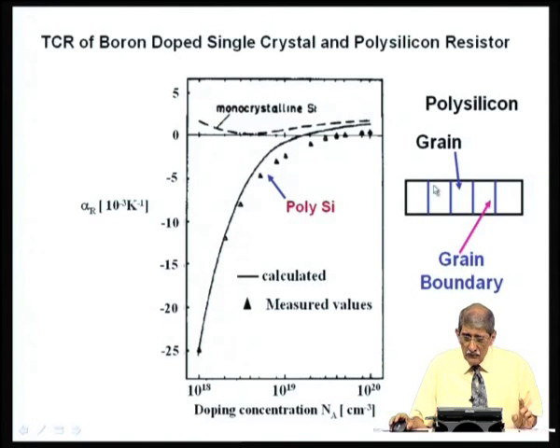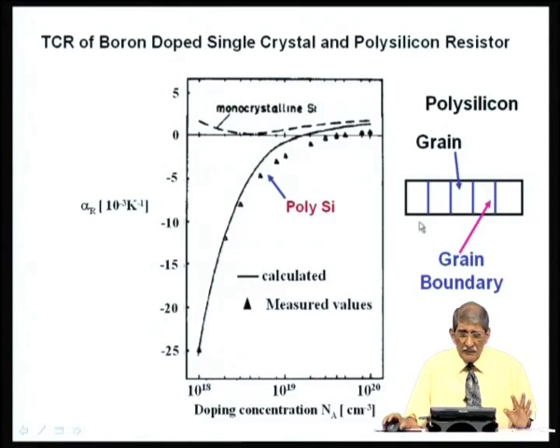Okay. Now, how much is the temperature coefficient of resistance? That is negative, depends upon how much the barrier is. If I keep on adding some dopants more and more, without getting into the mechanism of that, the barrier between these two layers gets reduced. Okay. So, if the barrier becomes 0, that will approach the single crystal, but we do not want that.